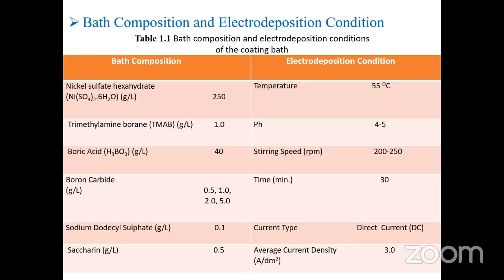Sodium dodecyl sulphate is an anionic surfactant. It reduces the surface tension and pitting on the surface by facilitating the hydrogen output from the cathode. It keeps the nanoparticles suspended in the electrolyte, so it can reduce the internal stress and prevent crack formation. It has the effect of a grain refiner.